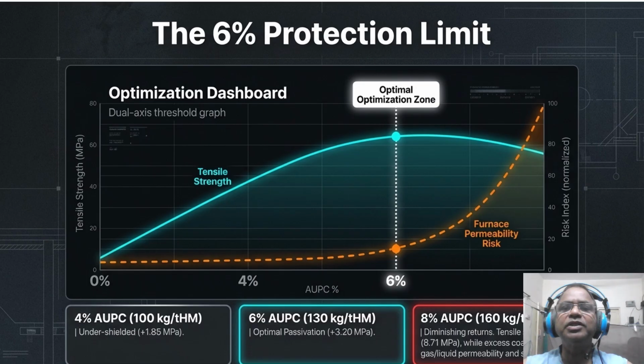The 6% protection limit. Is more always better? Definitely not. We have to talk about the risk index. Look at this dual axis dashboard. The blue curve is our tensile strength. The orange dashed line is our furnace permeability risk. At 4% AUPC, you are under-shielded. You only get about 1.85 MPa of recovery.